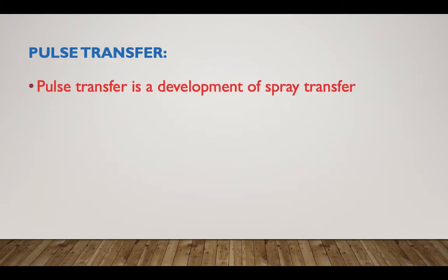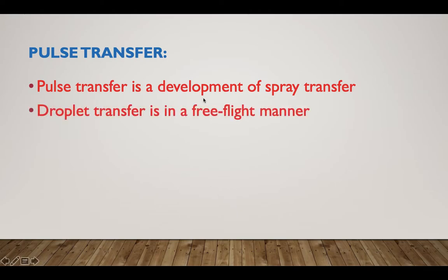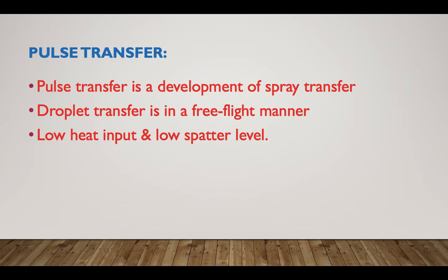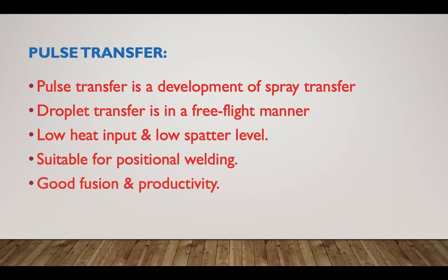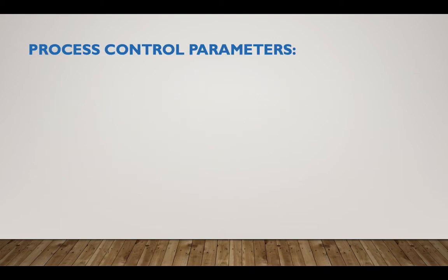Pulse transfer. Pulse transfer is a development of spray transfer. Droplet transfer is in a free flight manner. It is a low heat input and low spatter level process suitable for position welding. Suppose we have to weld in overhead position, then we have to choose this process. We can easily weld with the pulse welding process. Good fusion and productivity, used to weld lower thickness.